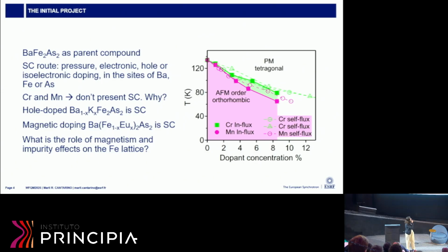So this was the phase diagram. I was interested in chromium and manganese doping of this parent compound. This parent compound is very famous for having many different routes to achieve superconductivity. You can apply pressure, you can substitute in different sites of the lattice to achieve superconductivity. But these two specific transition metal dopings don't give rise to any superconductor dome.